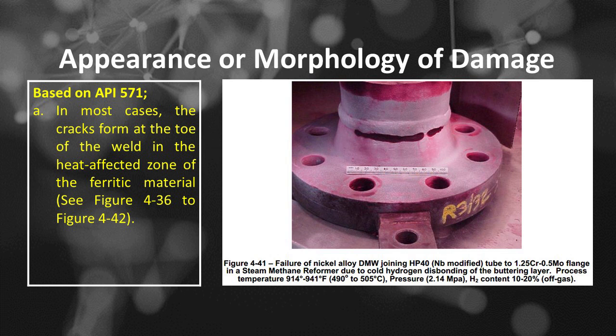See Figure 4:41, failure of nickel alloy DMW joining HP40, Nb modified, tube to 1.25 Cr 0.5 Mo flange in a steam methane reformer due to cold hydrogen disbonding of the buttering layer. Process temperature 914 degrees Fahrenheit to 941 degrees Fahrenheit, or 490 degrees Celsius to 505 degrees Celsius, pressure 2.14 MPa, H2 content 10 to 20%, off gas.